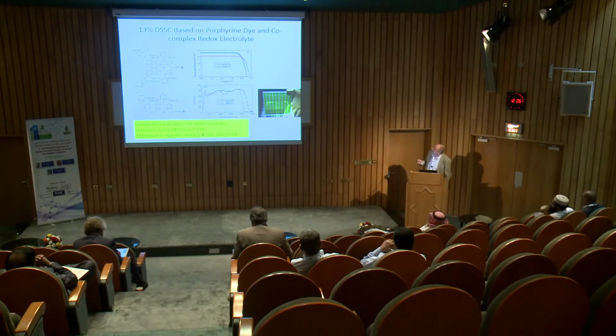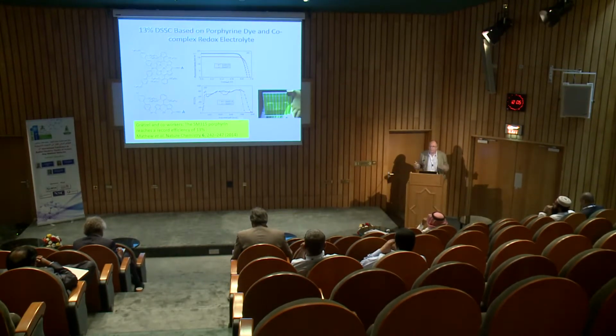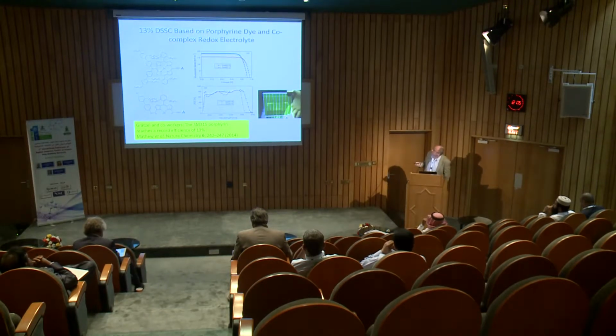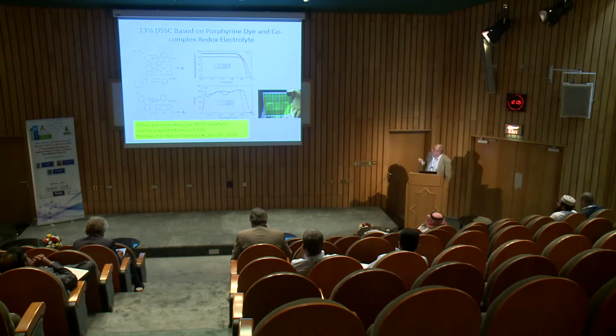and the best results at EPFL since 2 years back is with this zinc porphyrin dye molecule, and I know that Dr. Zakeeruddin will talk a bit more on the dye cells from EPFL tomorrow, but just to point out here that you also see the alkoxy groups on the side here following the design to passivate the recombination process, and the result here is done with the cobalt complex I just showed you at 13% efficiency, and you can make these nicely green colors and so on.